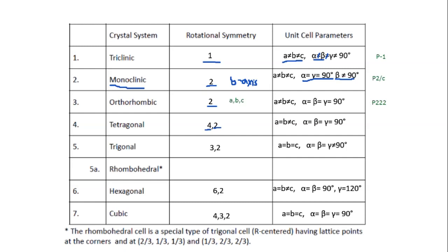So if you see fourfold symmetry, it's a good indication it could be tetragonal. However, cubic does have fourfold, but there are ways that we can distinguish between the two that we'll talk about later. Tetragonal is close to orthorhombic, except that A equals B and those don't equal C. So it has a little bit more constraint in the lattice parameters.